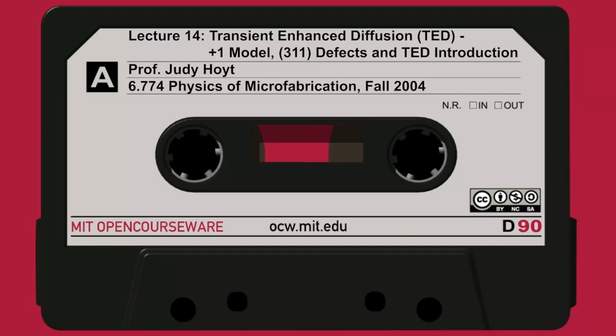The time is going to be the dose, Q, which is whatever I implanted, divided by that flux. Here's my flux. At the bottom of slide 18, I've just taken the dose and multiplied it by 1 over the flux. So the time to dissolve these clusters is going to be Q times Rp divided by the diffusivity of the interstitials times the maximum concentration, Ci max, the maximum excess concentration.